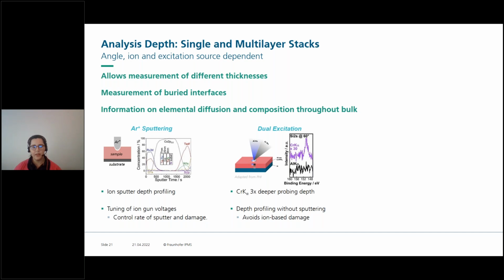What's also interesting about this is that we can therefore do depth profiling without the need of sputtering. And for any materials that are sensitive or degrade, this can help us avoid ion-based damage.